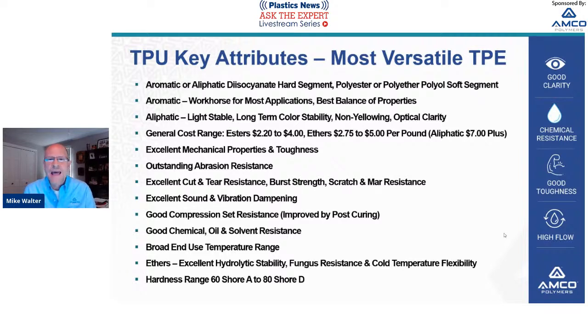The aromatics are pretty much the workhorse for most applications. They provide the best balance of all properties. The aliphatic grades are light stable grades. If you need long-term color stability with non-yellowing features and optical clarity, aliphatics is the way to go. General cost range, esters are around $2.20 a pound up to $4. Ethers around $2.75 to $5. And just in case you're curious, the aliphatics are north of $7. So I know cost does play a role. So you pay dearly for those unique features.